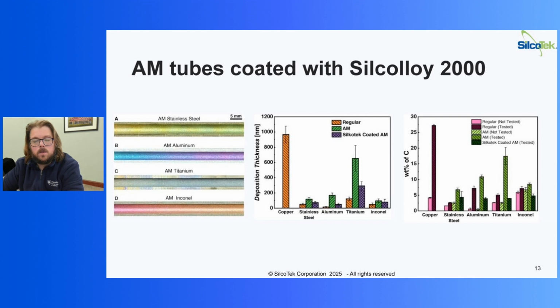And this is interesting for 3 reasons. One is every single one of those additively manufactured tubes saw less carbon buildup on it with the coating, so that's great. The second interesting thing here is you'll notice where you see the variation from stainless steel to titanium to aluminum to Inconel with the pure tube versus the variability with the additively manufactured tube. You can see in that dark green straight across, they all had relatively the same amount of weight that was deposited on the surface of those tubes. So it really brought in some consistency for their measurements.